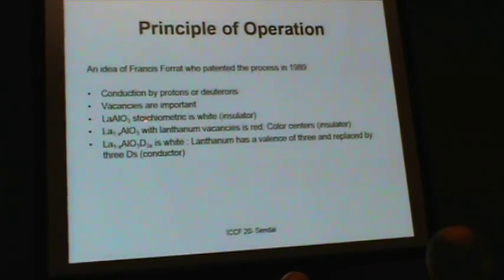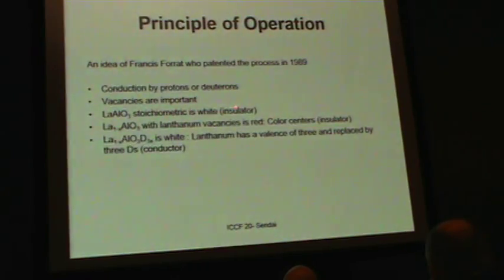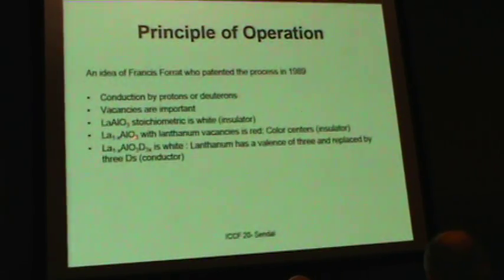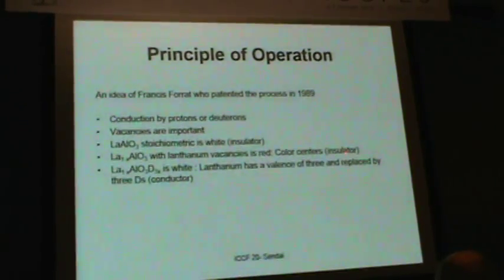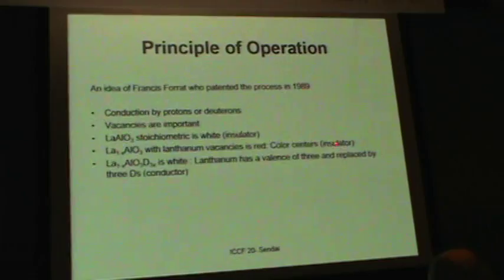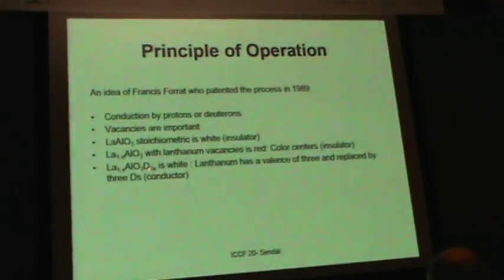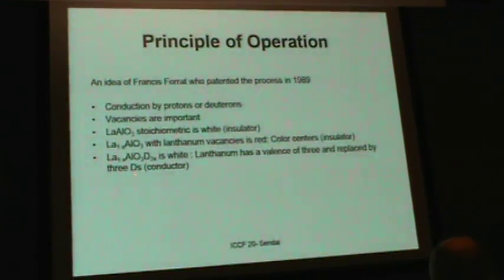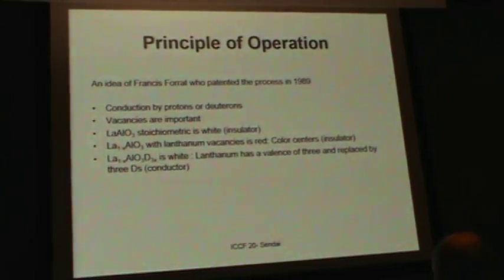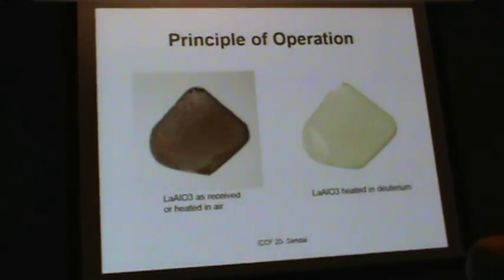You're using a crystal called lanthanum aluminum oxide. And when it's stoichiometric, it's white, the insulator. But if you have lanthanum vacancies in it, 1 minus X, then the vacancy makes color centers, and it becomes an insulator, but it is red. I will show you. When you put deuterium in it or hydrogen, the lanthanum, which has a valence of 3, is replaced by 3 deuterium. Let me show you what it looks like.